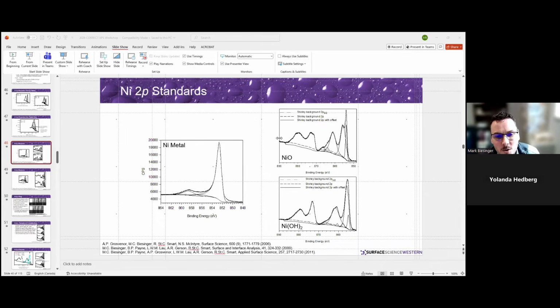Why do we look at the sharpest peak in the Auger knot and not the maximum peak? Is there any particular reason for that? Yes, there is. Sometimes that peak maximum is multiple peaks that move around, just like I showed with all those different Auger peaks that have different shapes. Certain Augers have a whole bunch going on, so the peak shape for certain species is not really definable at the maximum, whereas a different peak may have a much more uniform or sharp peak that's definable. It's situation dependent. So they go through and look at a bunch of different standards and say, okay, which one's going to work consistently, and it's not always the same one.